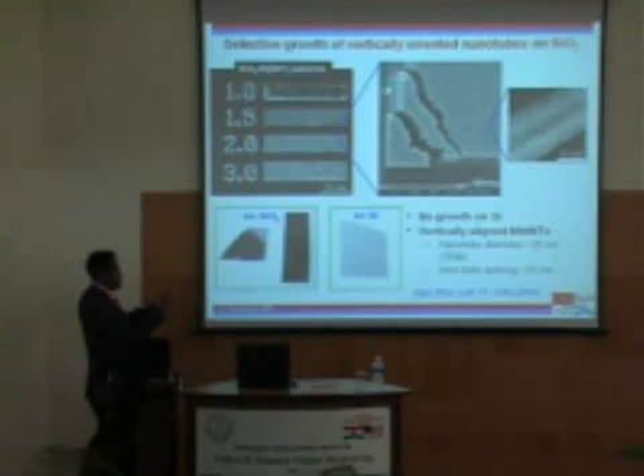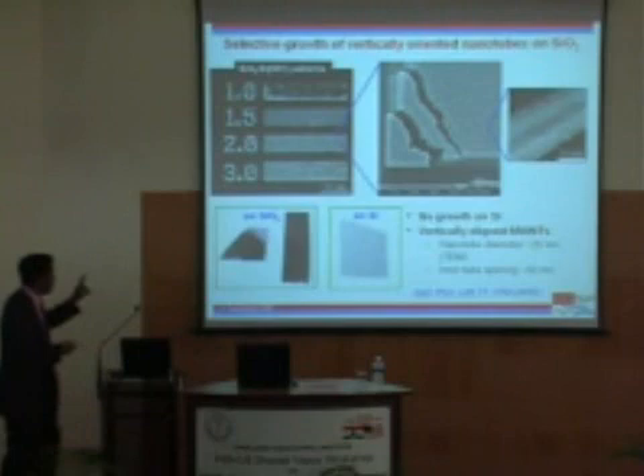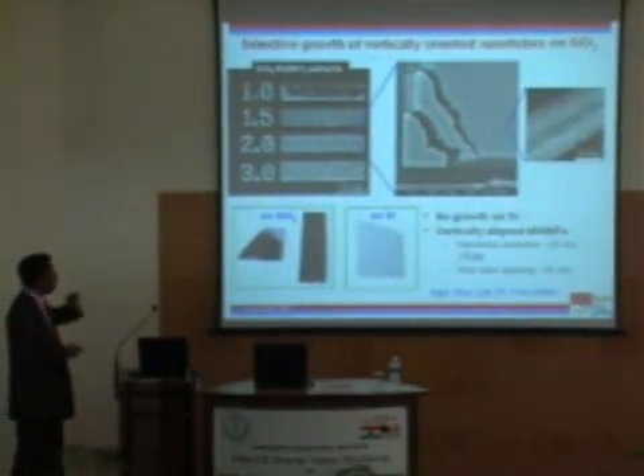There are two very remarkable things that happen for this particular chemistry. This is a scanning electron micrograph. The white regions are the regions where carbon nanotubes have grown selectively on silica. The black regions are silicon, where there is no growth at all. That is the first feature: growth on silica, no growth on silicon. And wherever you have the carbon nanotube growth, the nanotubes grow vertically, normal to the surface of the silica. So these are the two remarkable features, and you'll know why in just a moment.